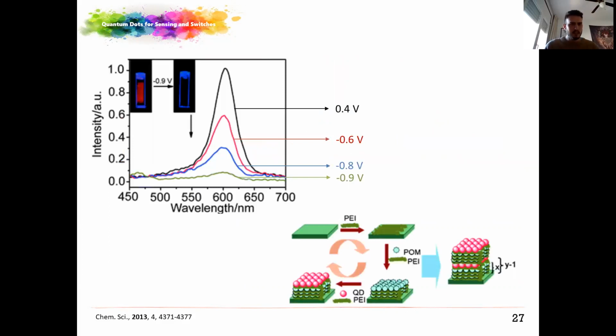So moving to switching applications, here the strategy is almost the same. For example, in this case, there is no electron transfer, but they are using the quantum dots in a multilayer with a polymer, which, after reduction or applying a lower potential, can change its absorbance. This absorbance corresponds to the emission wavelength of the quantum dot, and you can see here how the fluorescence intensity is changing, going to zero.